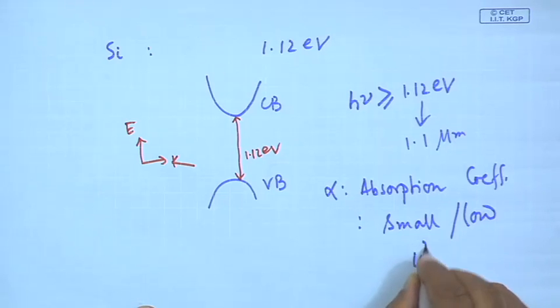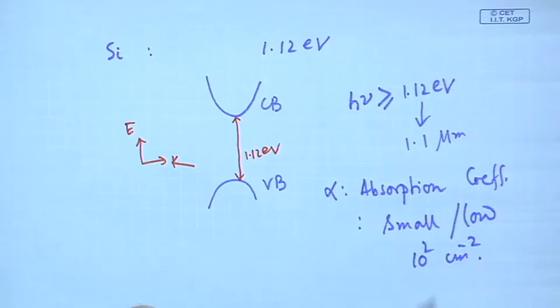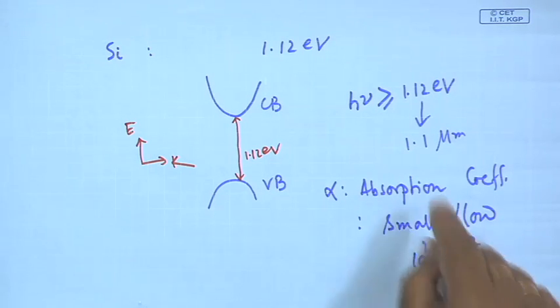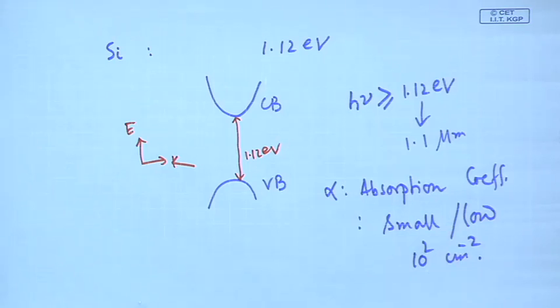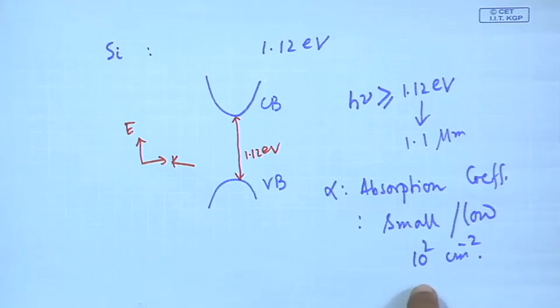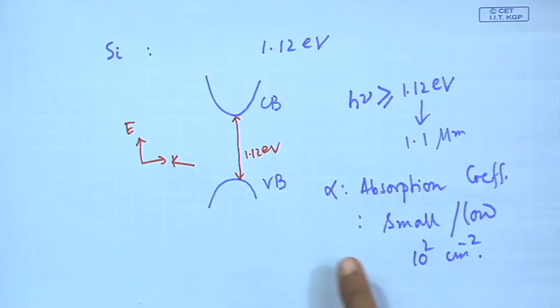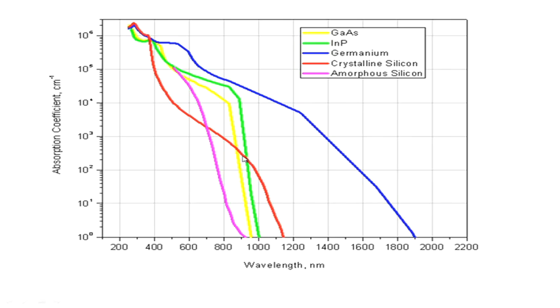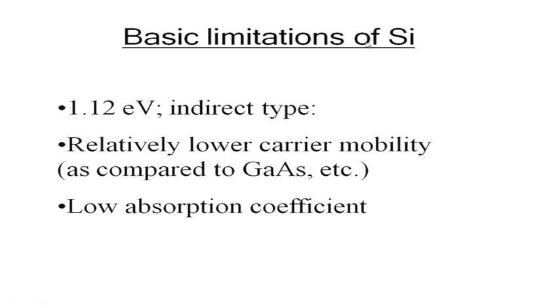It is almost 10 square per centimeter inverse. And if we compare with other types of material, say gallium arsenide, copper indium gallium selenide, or cadmium telluride, or amorphous silicon, we shall find that it is greater than 10 square. It is almost 10 to the power 4, 10 to the power 5 per centimeter, is the alpha value or the absorption coefficient value. So we can say that a basic limitation of silicon is its low absorption coefficient.